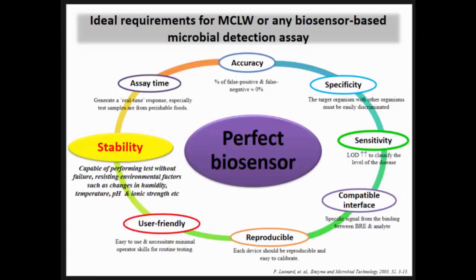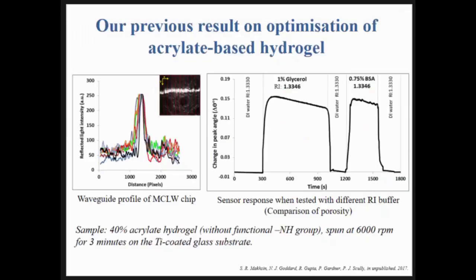Okay, so these are the criteria for a perfect biosensor. But today, I just focus on the stability, which is very important so that when we test the sensor, it does not give any failure and is stable during the detection. These are our previous results, where we optimized the composition of the hydrogel from acrylate-based polymer, and we got very good results, and we also require very good porosity for the structure. This is one test when we use the optical sensor for porosity testing, whereby we use glycerol as a small molecule example, and BSA as a protein, which shows the large size of molecules.